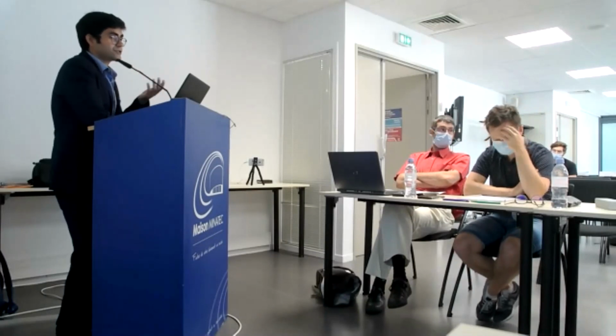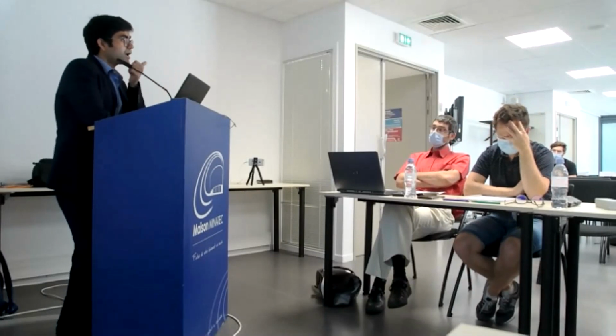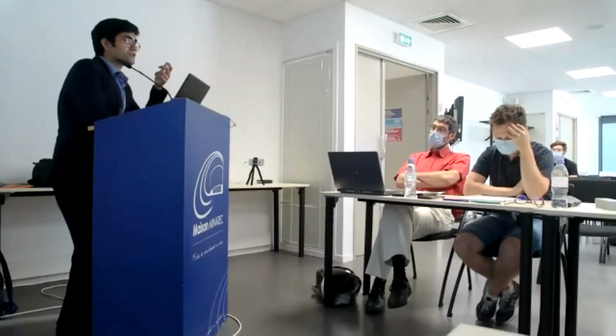Yeah, it is a good question. In fact, we had this in mind: compared to equilibrium conditions, at very high solidification velocities it's better to use Scheil-Gulliver since it can be a better representative of L-PBF, considering that Scheil-Gulliver always predicts infinite diffusion in the liquid, and you always have a prediction of microsegregation. But it's true that based on high cooling rates, your partition coefficient might be dependent on the solidification velocity. Based on that, we might need to recalculate the Scheil-Gulliver considering the partition coefficient is dependent on solidification velocity.